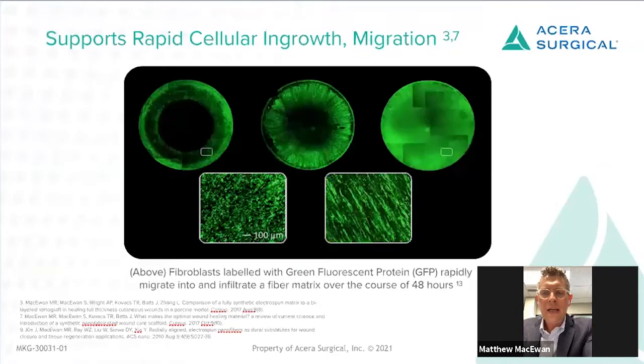into them very quickly. This is the results of an early study that we did that shows just how quickly cells can grow on and grow into these materials. In this case, we seeded fluorescent fibroblasts around the outside of our material up in the top left. And then at time zero, allow these cells to grow into the material as quickly as possible. And within just 24 and 48 hours, these cells actually grew into the material and started to replicate on the material. So it really shows you how quickly cells can grow on and grow into these electrospun matrices.